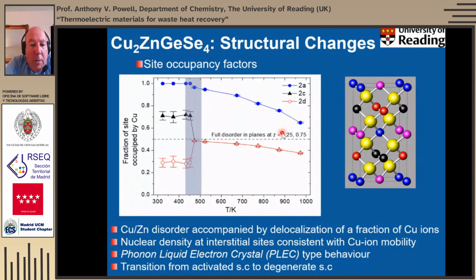So what we find is that the copper-zinc disorder is accompanied by a delocalization of a fraction of the copper ions. And in fact, by the time we get up to our highest temperature of 973 Kelvin, we find that the crystallographic formula involves about a 30% deficiency of copper. And when we do a difference Fourier map, we see that that copper is actually distributed over a whole range of interstitial sites in this structure. So it looks as if that copper sublattice is starting to melt. So it looks like phonon-liquid electron crystal type behavior. And that's associated then with this change from an activated semiconductor to a degenerate semiconductor.